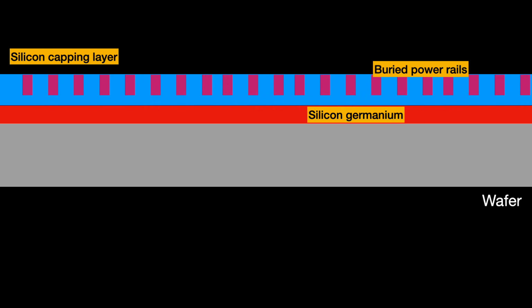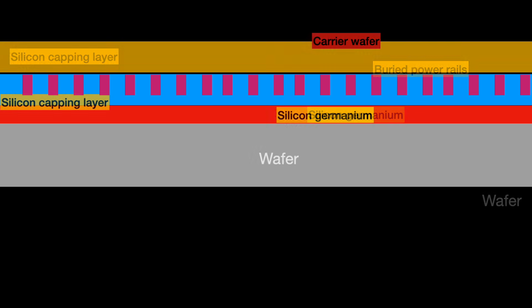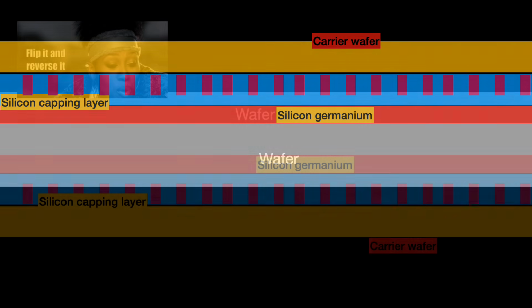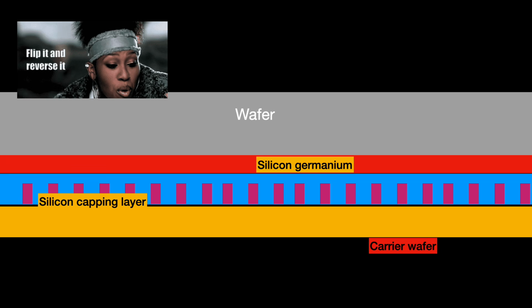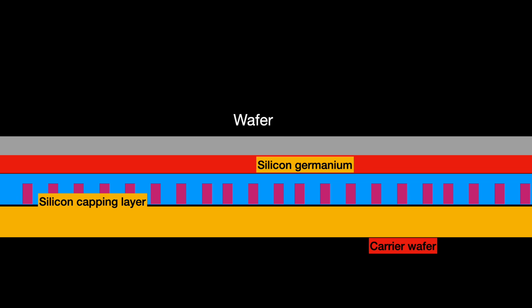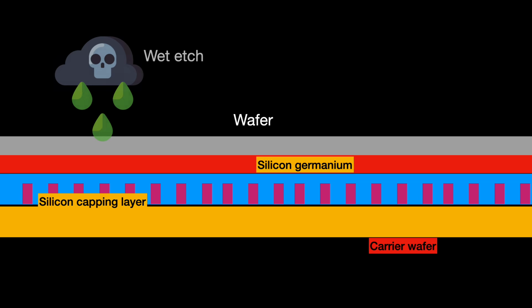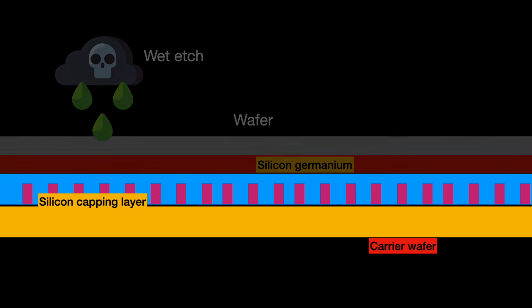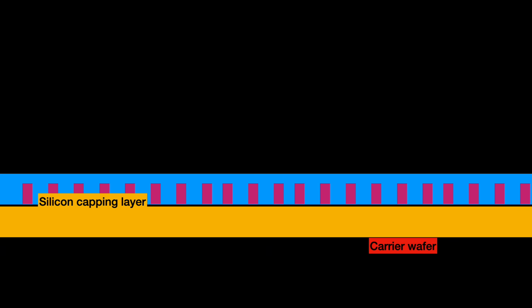Then we bond on another wafer on top of all of this. This is called the carrier wafer, because we are going to flip it like Missy Elliott did. The carrier wafer, at first bonded on top, is now on the bottom. We then grind down the original wafer's backside in a series of steps. First, we use a grinder, then a polisher, and then finally semiconductor etching tools like dry etch and wet etch. Last is the wet etch, which involves applying acid to eat away the aforementioned silicon germanium layer and exposing the very flat capping layer. We are now ready to dig the through silicon vias into the silicon layers to connect the buried power rails to the power network.